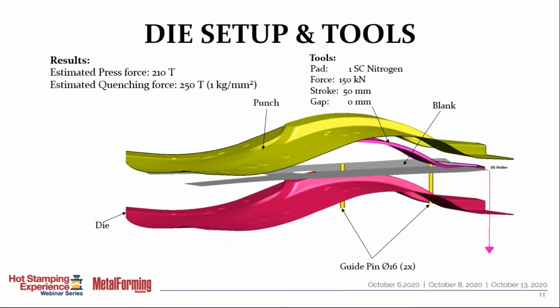And that's because of the high coefficient of friction on the parts, which is kind of the reverse of a cold stamp process. So in this case, we felt that we would have wrinkling problems in this area if we did not have a pressure control pad. And in hot stamp, we use basically a force pad that can hold the part in position during forming, or we have a gap pad that provides a small gap to allow material flow.